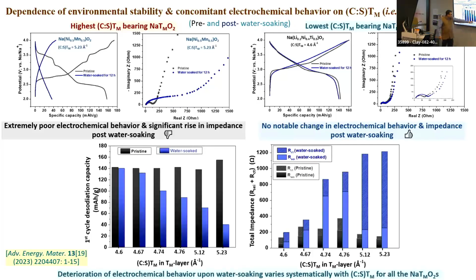Then, as I told, the one with the intermediate charge to size ratio follows suit when it comes to the degradation of the first cycle capacity after water soaking. So this is perfect, this is very bad, and there is an increment in the impedance after water. Now, the point to note here is that it is the charge transfer resistance which increases drastically, which means that it is not just the formation of surface residual species, but the damage done to the structure, which is highly significant, especially for these transition metal oxides, where the charge to size ratio is very high and which are highly unstable when soaked in water.